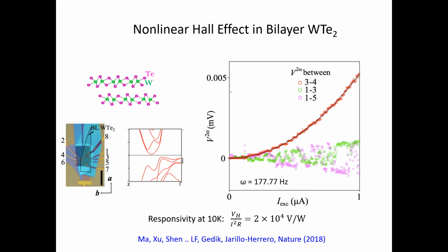And this is a result of their measurement. Again, to single out the second order response, they applied an AC current, very low frequency of about 100 hertz, and they locked in to a frequency of 2 omega. And you see that this effect arises when the voltage is measured in the transverse direction, okay?